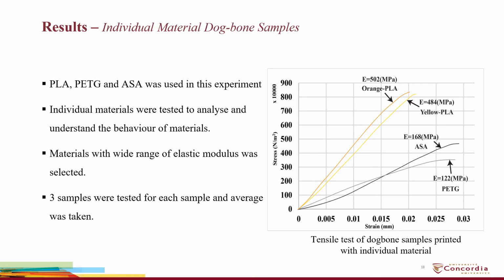To understand the properties of individual materials, we analyzed dog bone samples printed with PLA, PETG, and ASA materials. As we can see in the tensile test graphs, that we selected materials with clearly different mechanical properties, and this enables us to correctly assess the enhancement in mechanical properties only due to interlacing and interlocking features.